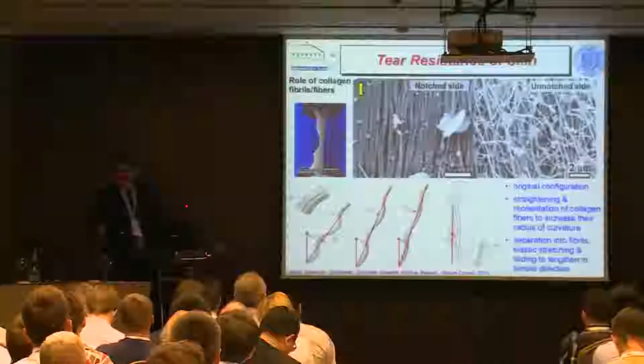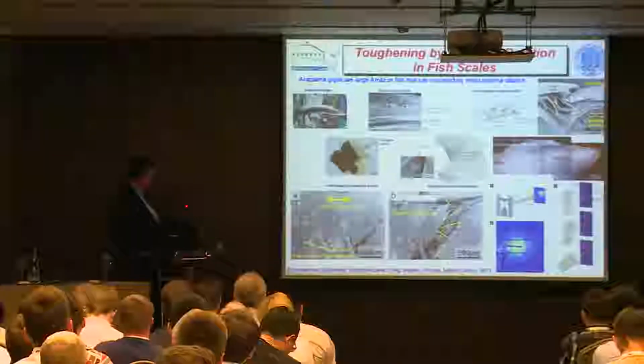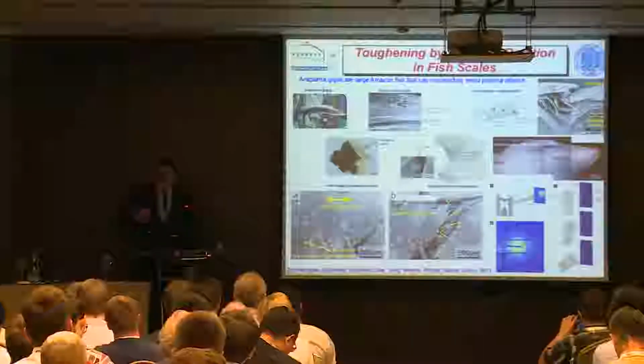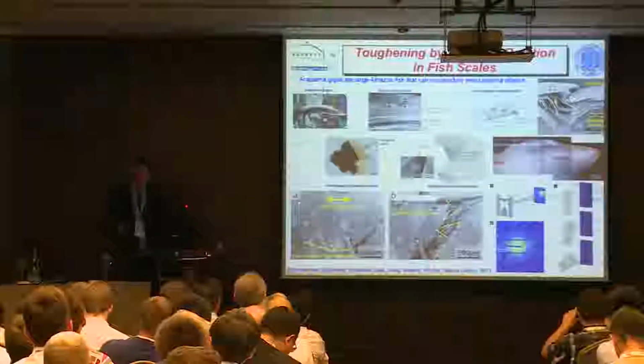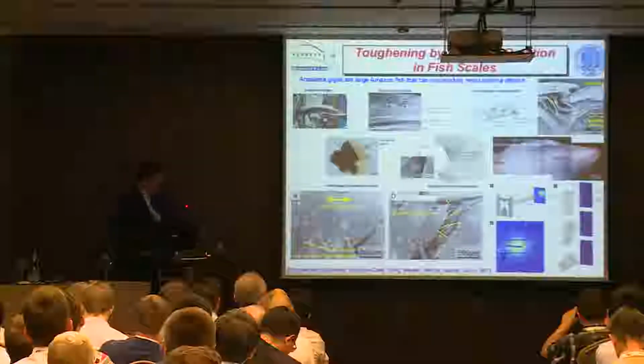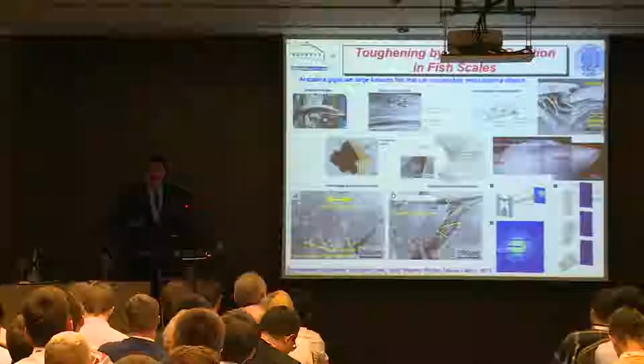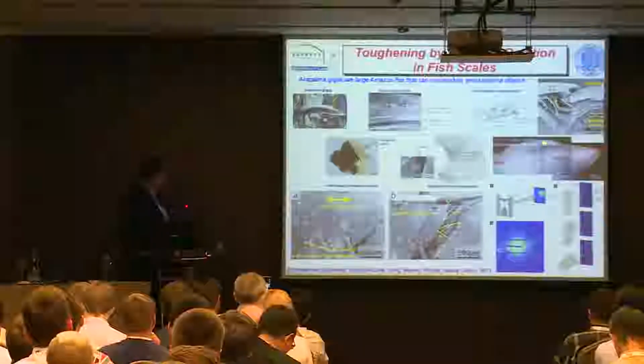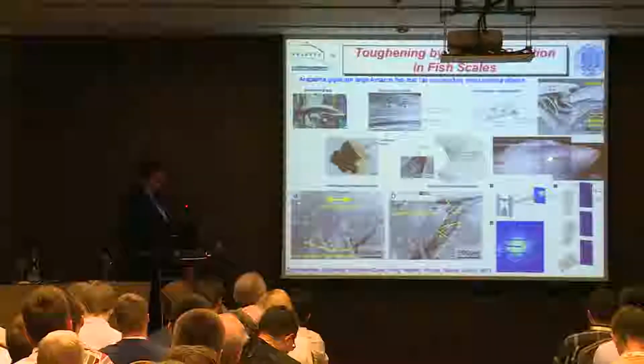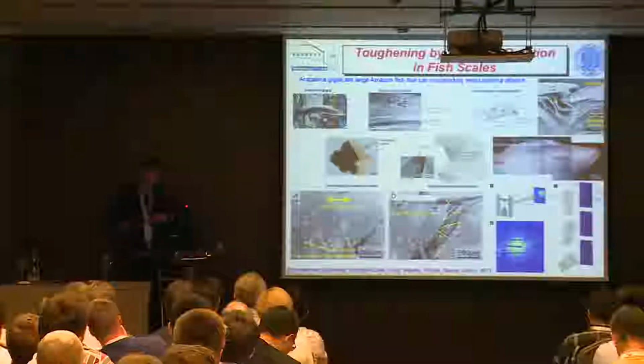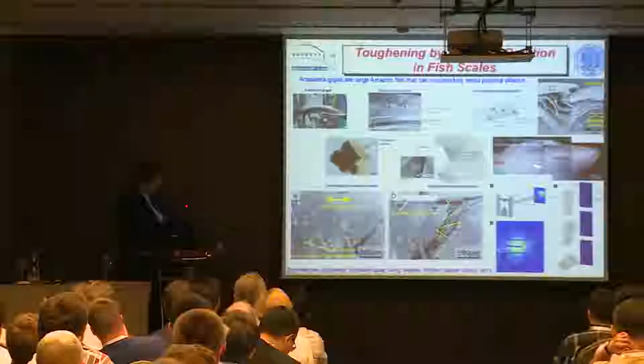Now it's funny, these fish scales are kind of similar. We've also looked at fish scales. These are not pure collagen, they have mineral in them, but a classic armor will have a very hard surface which resists penetration. But if the whole material was made of that, it would just shatter. So there's generally a softer but tougher sublayer or inner layer, which then accommodates the extra deformation. And in biological materials, this is just changing the mineral content. It's more mineralized on the surface than it is in the interior. And biological materials always do gradients very well, and they morph out any sharp interfaces. So there's a beautiful gradient in mineralization as you go from the hard surface to the subsurface.